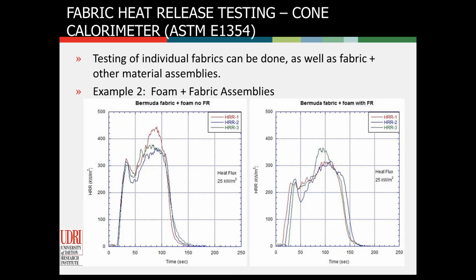Here's another example where I mentioned foam and fabric assemblies. So here on the left, if I remember correctly, this is a cotton polyester Bermuda fabric with a polyurethane foam. We made one of these little cushions I was describing. There's no flame retardant in it. So you see the heat release on the left, and then when you put the flame retardant in the foam, you see that the heat release begins to decrease over on the right, indicating the flame retardant's having an effect, and then the fabric's just kind of along for the ride in this particular case.